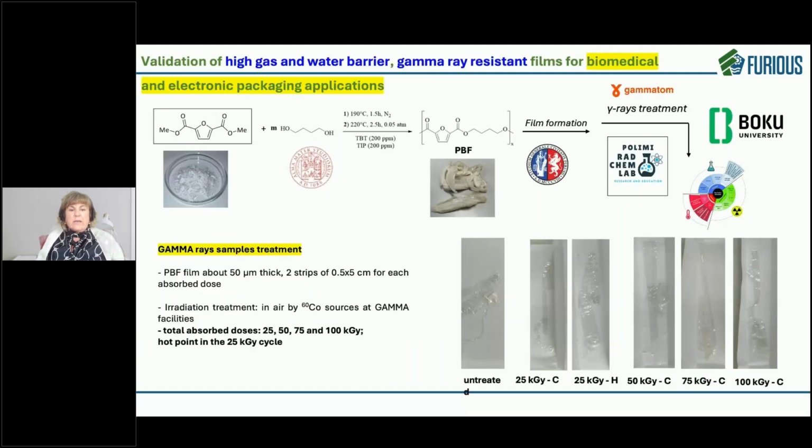And last, the study regarding the interaction between our polymers and gamma radiation. Gamma radiation, as said by the colleague Debora Puglia, is necessary to sterilize our packaging for biomedical applications. We saw that the dose of 25 kilogray does not affect at all the performances of our polymer, which maintains all the target properties at the optimal level.